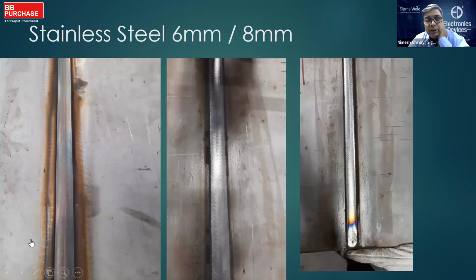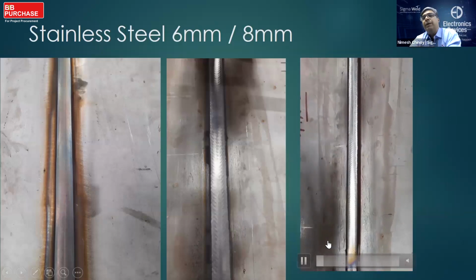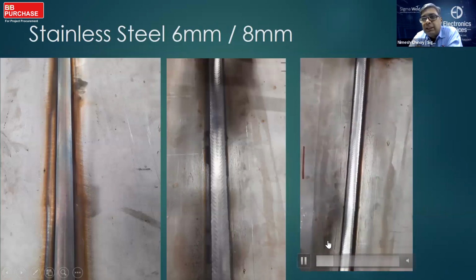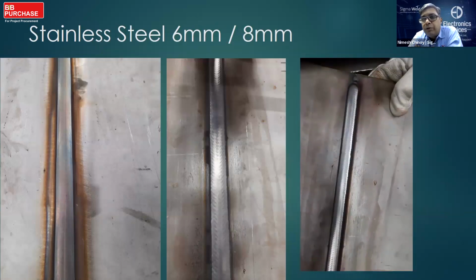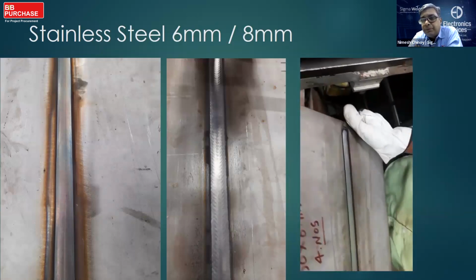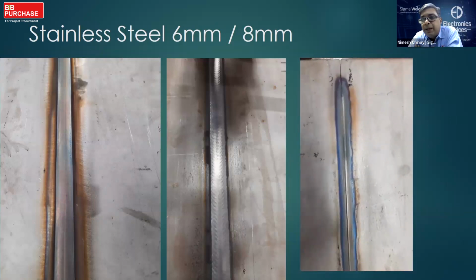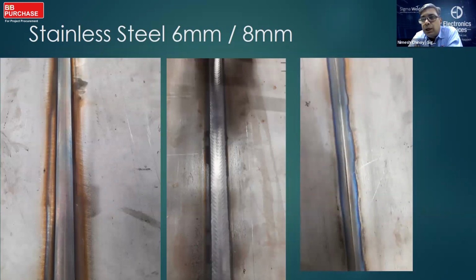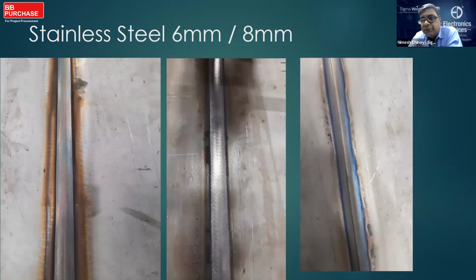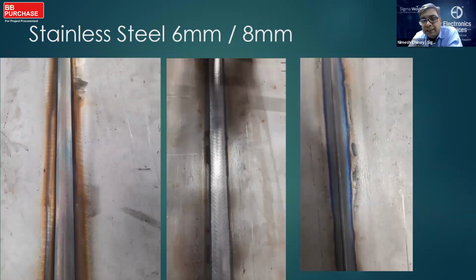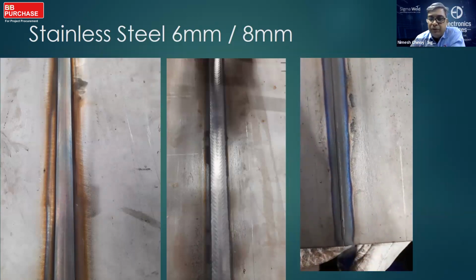This is for a customer using stainless steel, manufacturing stainless steel long seams, plate to plate. And you can see the weld finish. This is achieved at about 400, 450 millimeters a minute. It's a 6 mm thick plate. All root, RT, other were passed as per section 9 of ASME code. This is a bead finish you can get.